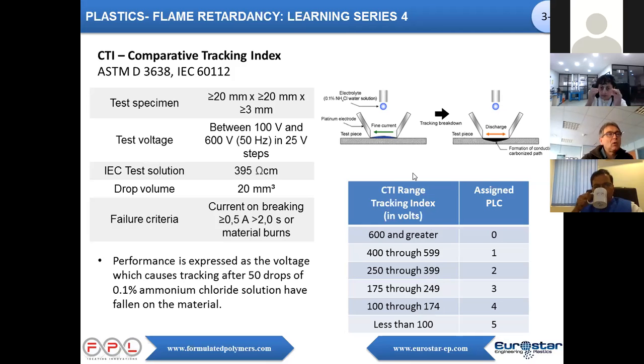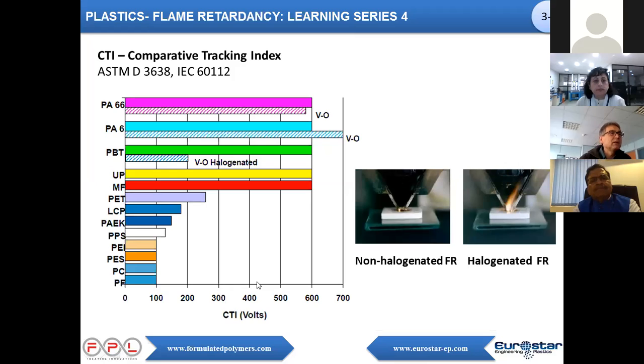There is a lot to say on this testing. Electrodes are in platinum, and it's very important because sometimes, for cost reasons, people use electrodes in brass, but you can have interaction and creation of conductive ions. For example, for some halogen-free materials, if you have a brass electrode, you can create a kind of conductive copper-phosphorus system that makes the material conductive. So it's very important if you compare the CTI of materials.